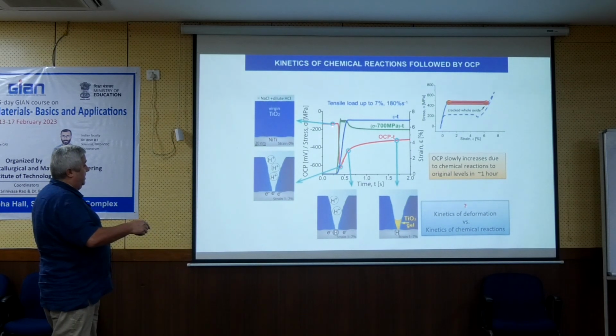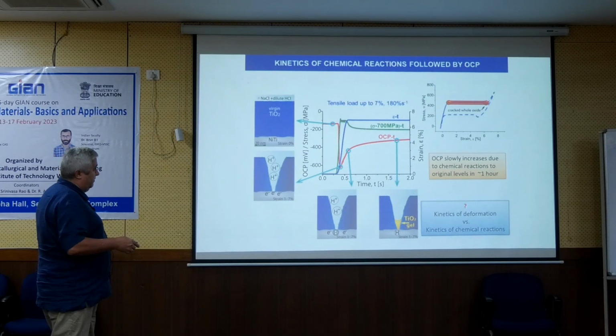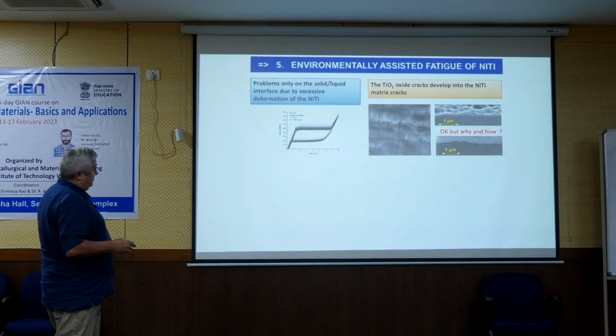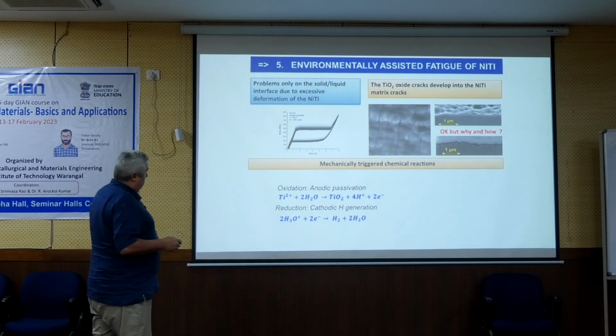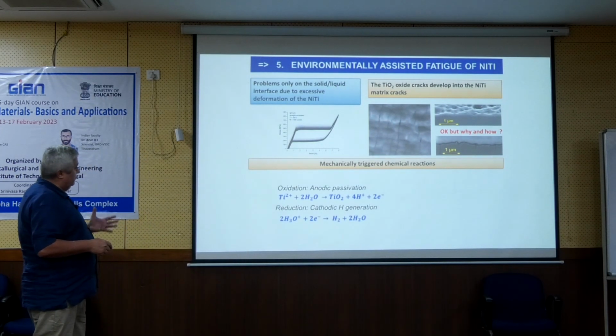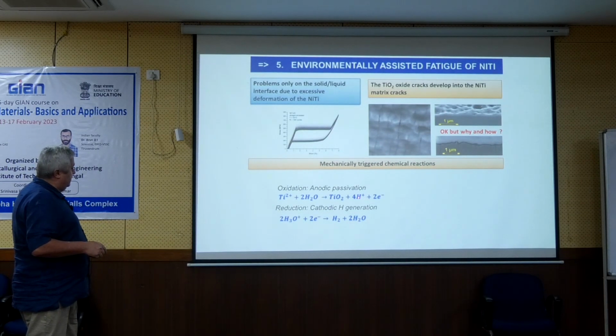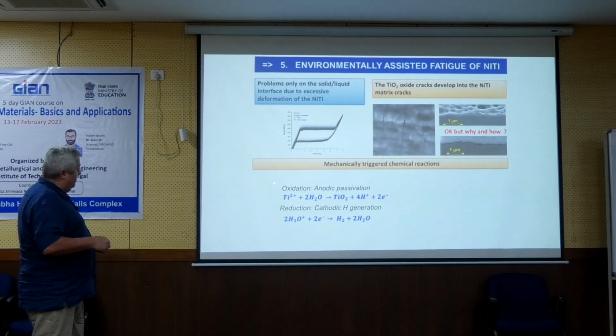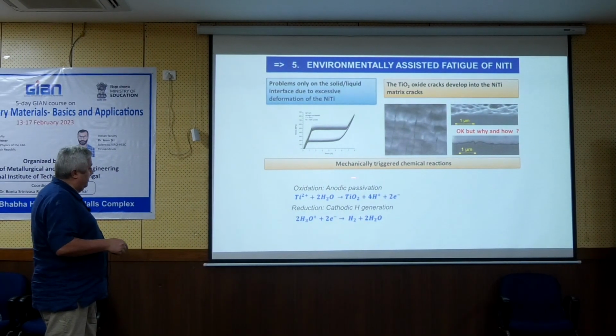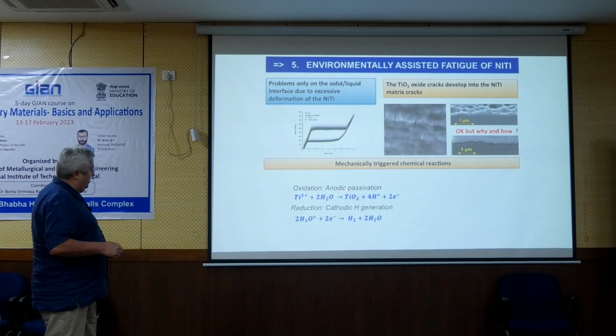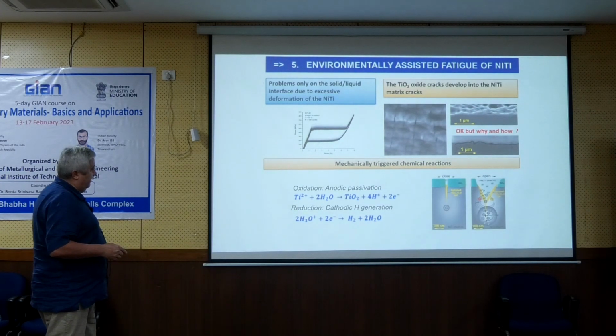If you cycle elastically only, there are no cracks. This OCP will stay approximately constant. So this can be explained basically as two different chemical reactions, which are classical ones: anodic passivation and cathodic reduction, which proceed simultaneously in the moment when the bare metal is open, is put into contact with the liquid.